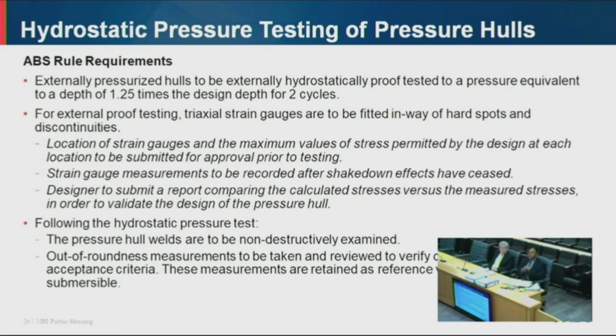So in new construction pressure hulls, you will notice localized areas of high stresses on the hull. When you pressure cycle the hull above its design pressure, these localized areas of high stresses start deforming, okay? So you'll have localized deformation and then strain hardening occurs. Once the strain hardening occurs, no further deformation of the hull occurs plastically. All the deformation is in the elastic region, okay? So that is when the shakedown effects cease.